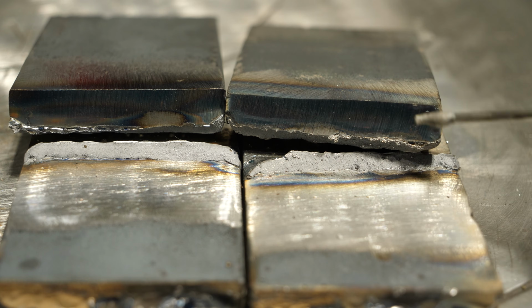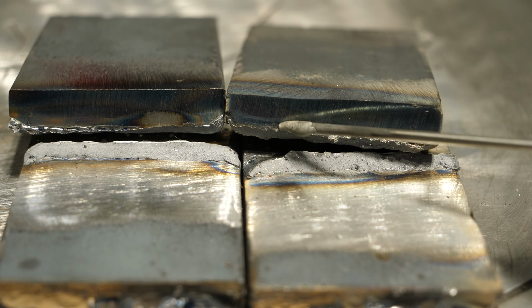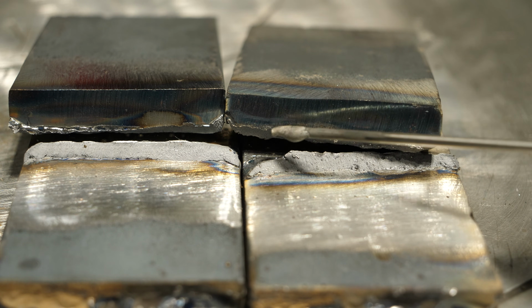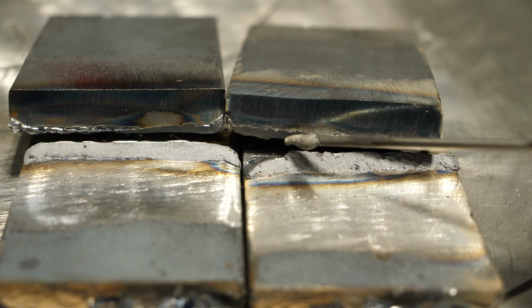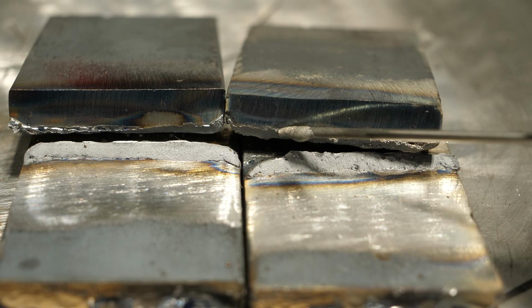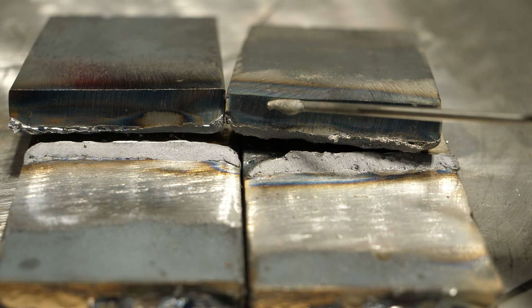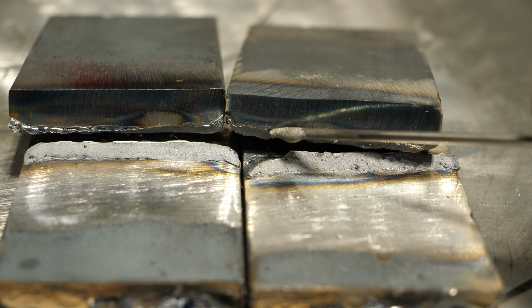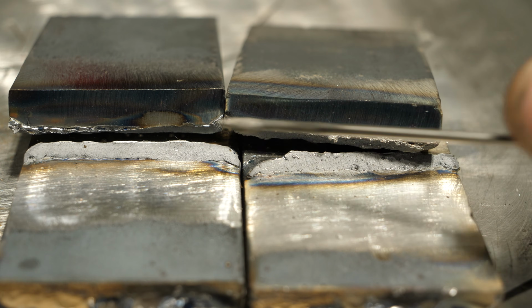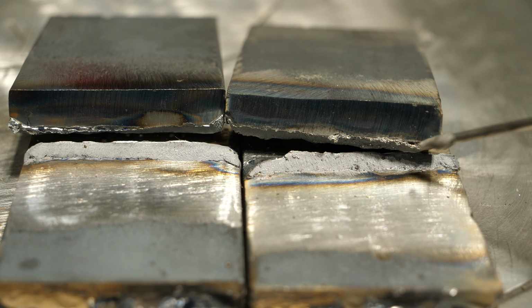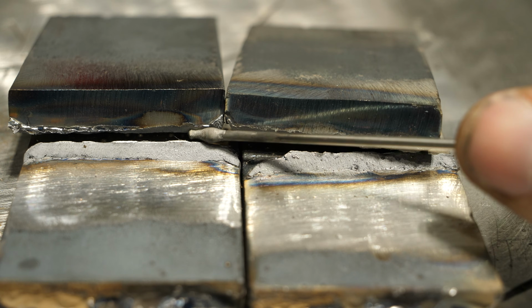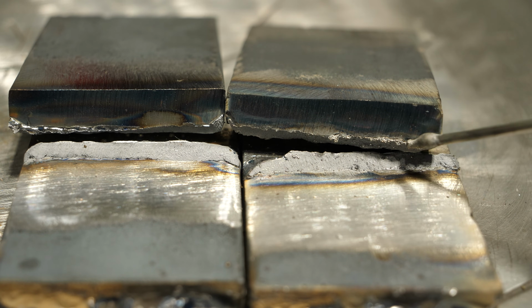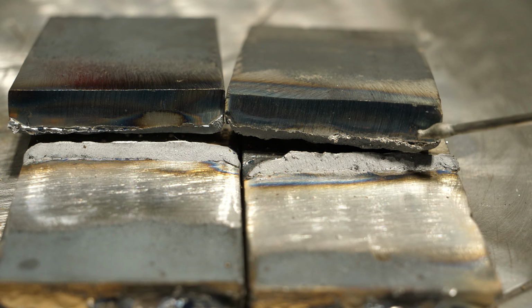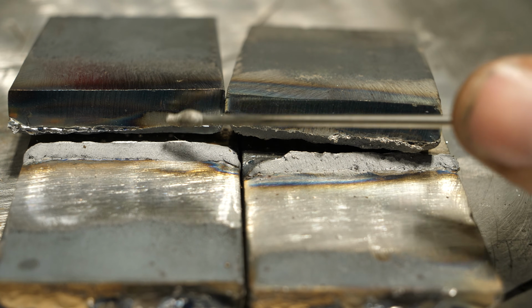When you look at this flux core weld, you see the distance between here and here, how it's much thinner than here? That's because this wire penetrated into the root, chewed away at it, and fused it, and then breaking it, it broke further into the plate than here. So here it's less. We can see evidence of the original edge of the plate. So less penetration here, but the overall weld, I mean, 80% of it here had more penetration than on this.